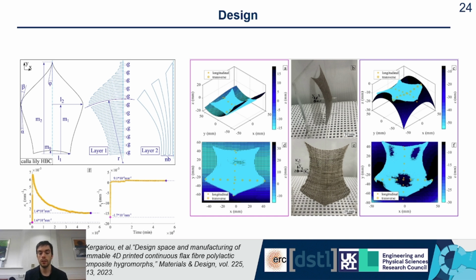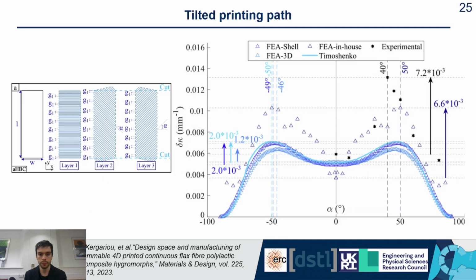So we wanted to implement a technique to improve these two aspects, increasing the actuation amplitude. This was the role of this specimen that we've shown already several times during this presentation, in which you have different angles for the different layers. We wanted to see if the angle alpha can modify the amount of actuation that you get in the specimen. So we varied the angle alpha and tested different values, and we were able to see that at 40, 45, and 50 degrees, you obtain much more actuation than at any other orientation. Usually for actuators, most people use a 0/90 stacking sequence, so a value of alpha of 90 basically, and we proved that we are able to increase the amount of actuation by changing this angle alpha.